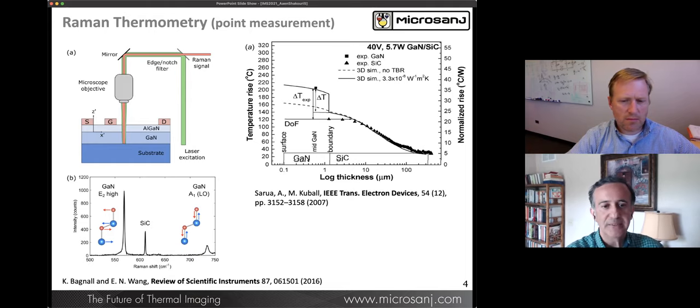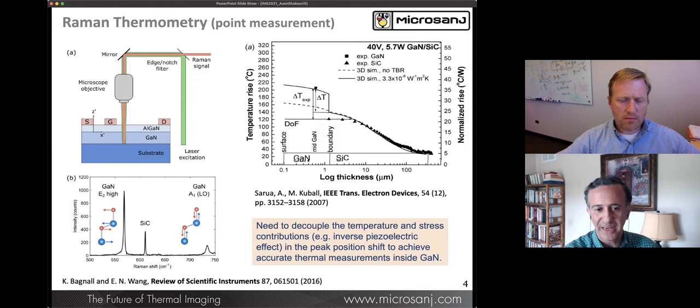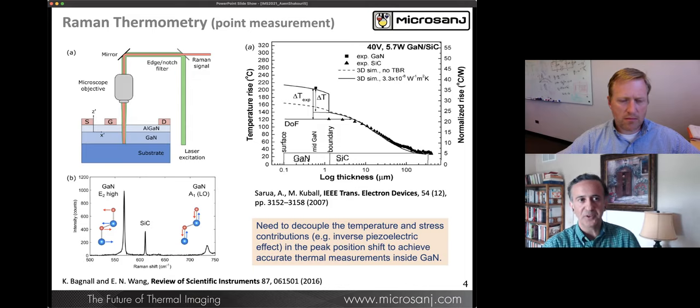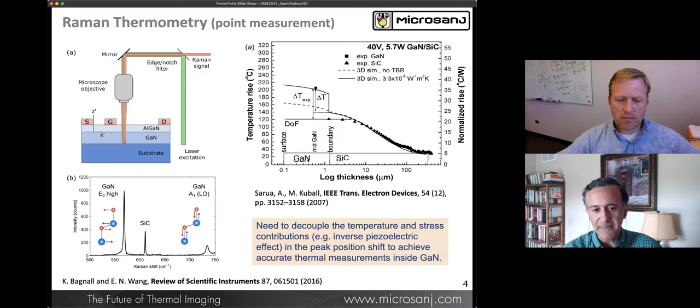While this is accurate, there is a real challenge: the peaks in the Raman are also affected by stress, such as inverse piezoelectric. So detailed calibration and sometimes modeling is needed to get accurate temperature measurement. It takes quite a bit of time to do an image by scanning. But the advantage of 3D is valuable to look at substrate effects.